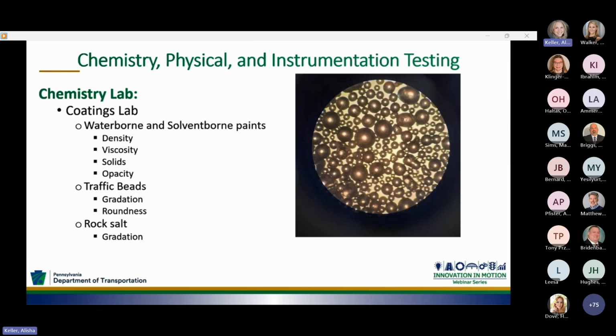For traffic beads, we test for gradation. We don't want the beads to be too large where they're taken up by snow plows, and we don't want the beads to be too small when they're placed on the surface of the paint that they just blow away or even sink to the bottom. We need a mixture of all size beads. We also test for roundness. Each specific sieve must be 70% round, and overall, the beads must be 75% round to perform well.